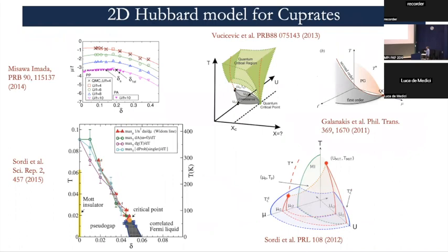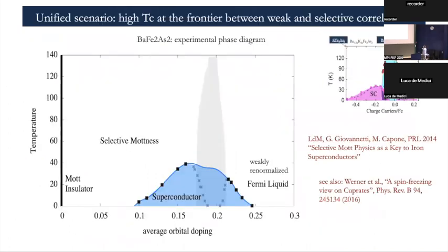Now, just to conclude, there is a parallel that you can do with models for cuprates, where indeed you have the same phase separation zone emanating from the Mott transition, and it's centered where the superconductivity is centered in the experiment. That's why we manipulate this phase diagram of iron-based superconductors in a way that if you plot the density as average orbital doping, you find something very similar to the phase diagram of cuprates, with a Mott insulator, a selective zone that corresponds to the pseudogap or zone where you have heavy and hot and cold electrons in the cuprates, a superconducting dome, and weakly correlated Fermi liquids at large doping.